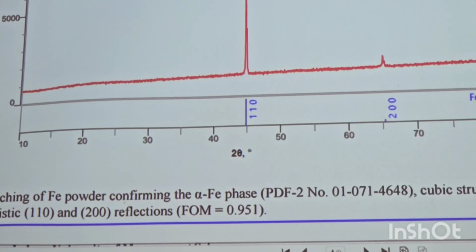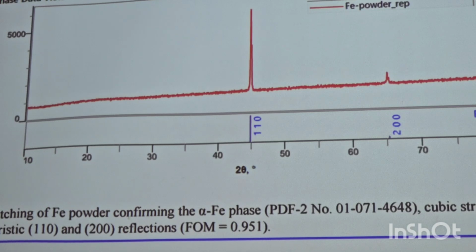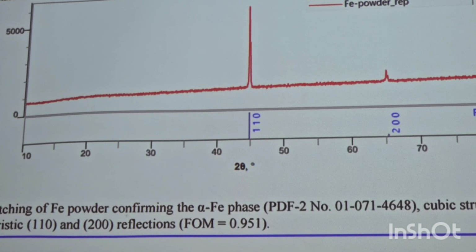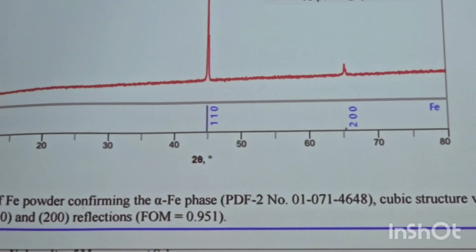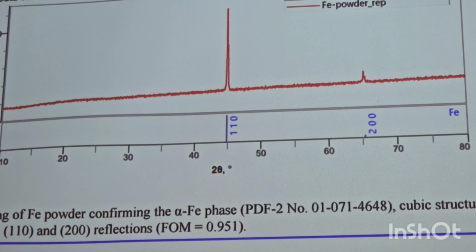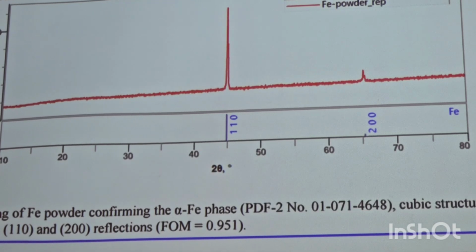This is iron. And here you see that only those peaks exist for which the sum of the HKL indices is even, and there is a dependence of the intensity on the theta.